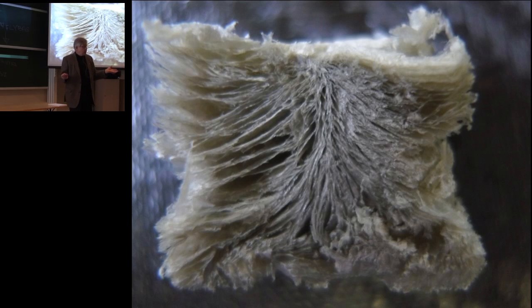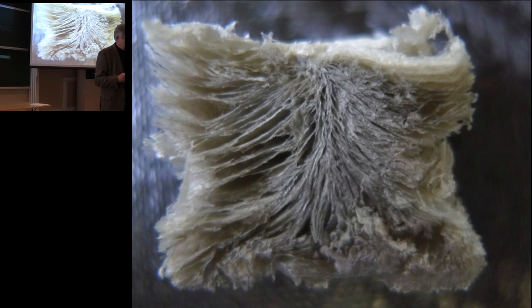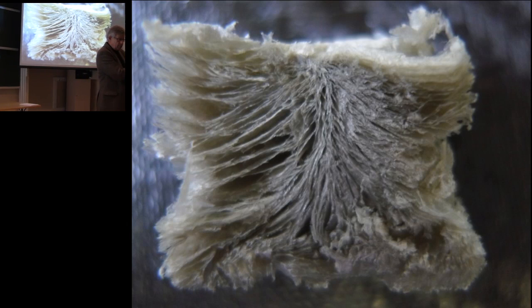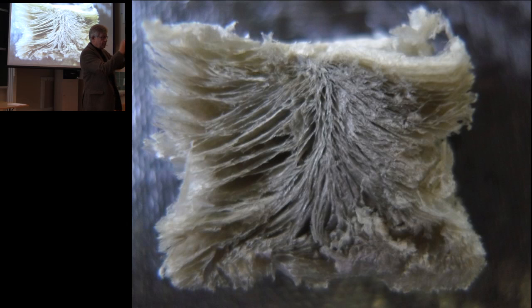Because when water turns to ice, it releases energy. Right? You know that it is slippery when just around 0 degrees. And this energy is a local boiling. Sometimes you see small voids in ice, right? And when it's just freezing, this energy goes out, you get an energy center, and all the ice crystals are turning into the heat center. And in between comes our nanocellulose fibers. So by using the freezing front, I can decide in what direction I will have the nanocellulose fibers in my foam and the properties of my foam. This knowledge is less than half a year old.